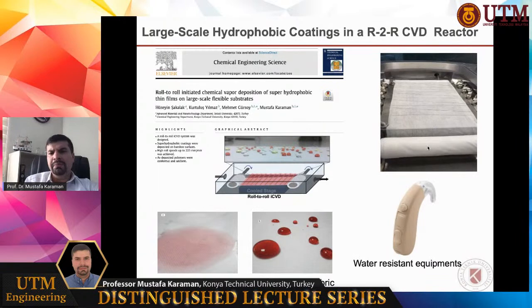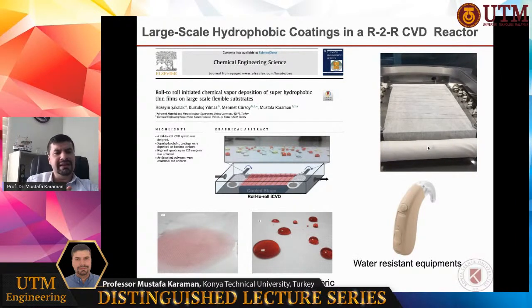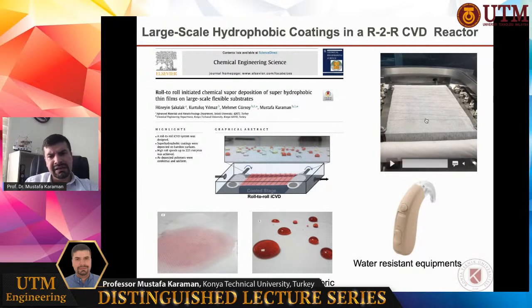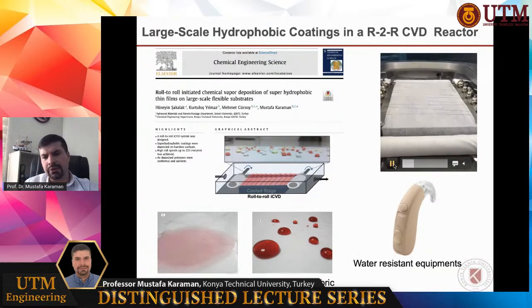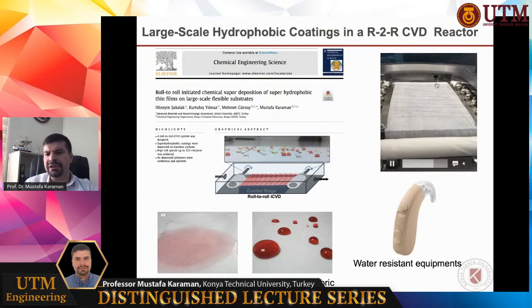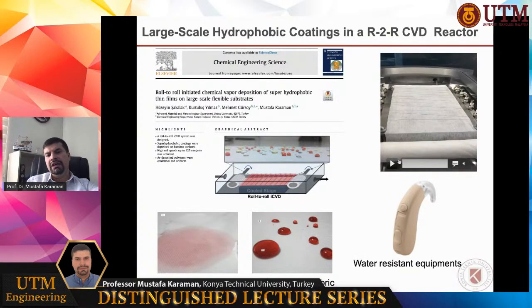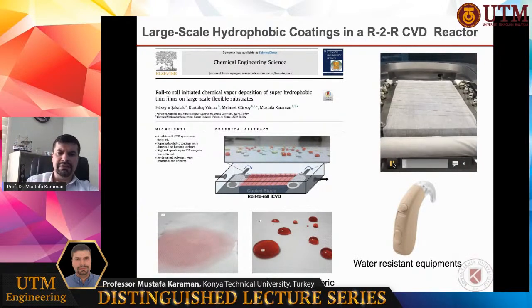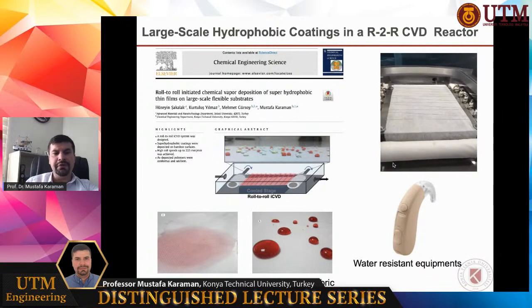We also developed roll-to-roll systems to make large-scale coatings. As I said in the beginning of my presentation, Turkey is a textile country, so many textile companies are interested in our technology. That's why we developed this roll-to-roll system to functionalize fiber surfaces. Roll-to-roll iCVD, as far as I know, is one of the first examples of iCVD in a roll-to-roll system to make superhydrophobic thin films on flexible substrates. Here, we use bamboo fabric. Bamboo is a very hydrophilic material, and after coating in minutes, we could obtain ultra-hydrophobic bamboo surfaces, which can be used in many different applications. And the durability of our coating is very high.